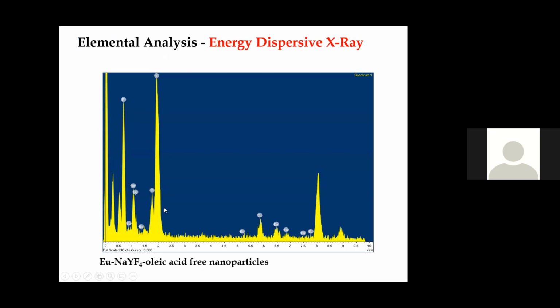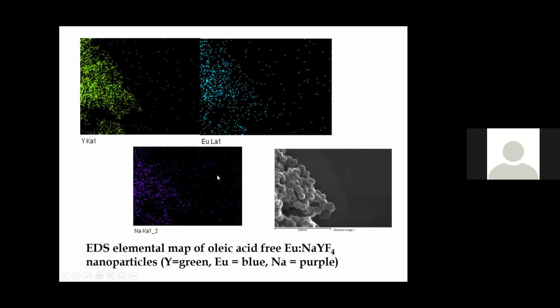Another method that we use to characterize the nanoparticles, the elemental analysis, is called energy dispersive X-ray. You shine high energy electrons on these, and they eject X-rays from inner orbitals, and those are characteristic of the element. So pretty much you can get the elemental composition here. Your x-axis is kiloelectron volts, the energy of those X-rays emitted by inner orbitals. Your y-axis is the intensity. So here we prove that we have europium, sodium, yttrium, and fluorine. We can map these elements using EDS, energy dispersive X-ray techniques. You see the distribution of your yttrium, europium, and sodium. You see the sodium is low, and you can count or quantify these amounts.